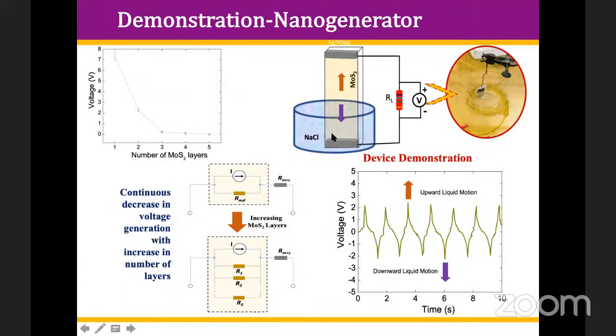Then we tried one experiment where we put the NaCl in some beaker and shook it using the shaker, and you can say when it is going up and down on both sides, we are generating the voltage going up and down. It clearly shows that this device can be used for practical applications. And by using the number of layers, if monolayer is there, generation is more and more, and if you are increasing the number of MoS2 layers, the current, voltage and power are going to decrease.